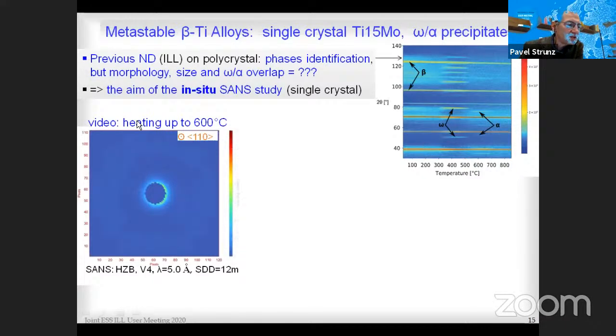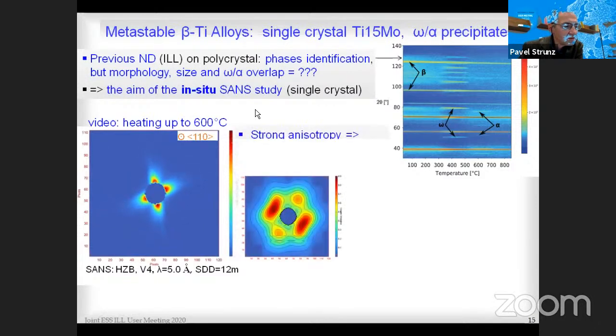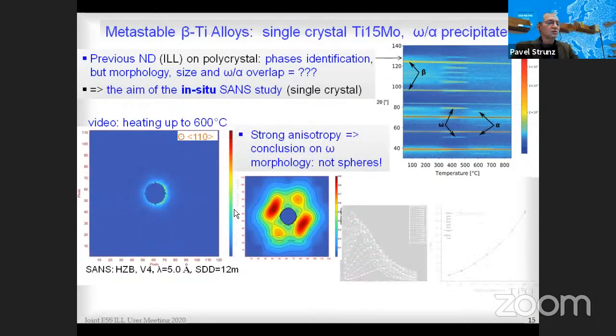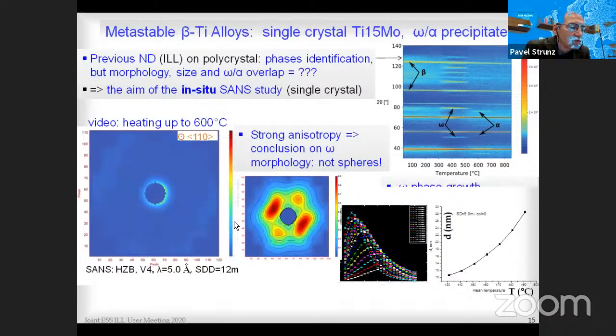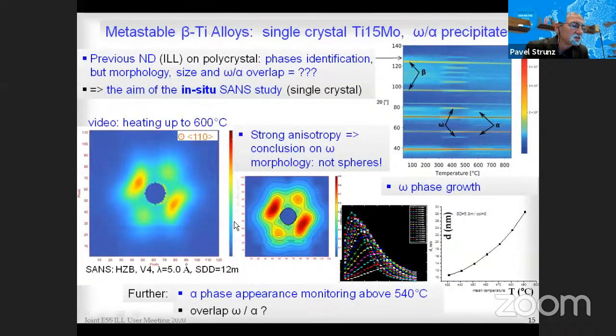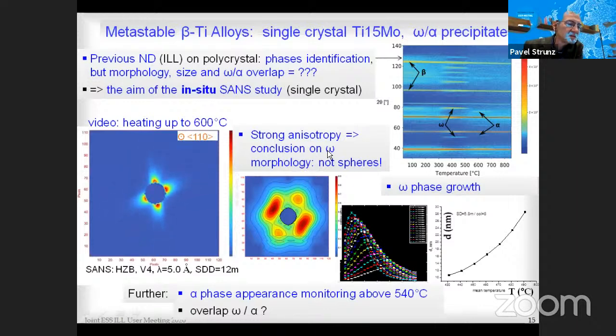The video here shows the scattering patterns from the in situ heating of the material up to 600 degrees centigrade. As the scattering patterns are strongly anisotropic, we can conclude about the morphology of the precipitates. And it is quite true in this case that there are no spheres, but the omega precipitates are rather prolate spheroids. And we can also conclude on the omega phase growth, which is